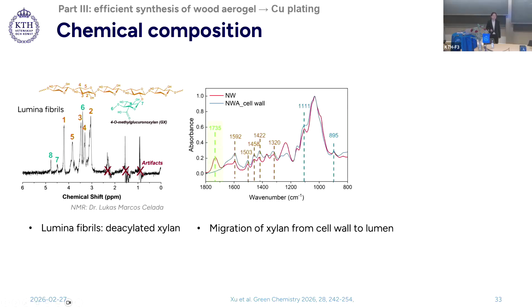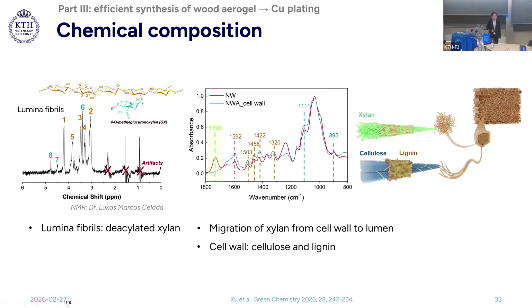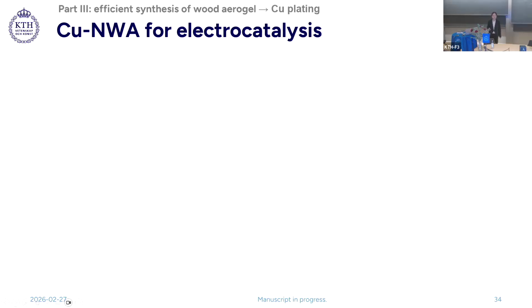Meanwhile, characteristic bands of lignin and cellulose remain. In a word, the lumina fibrils of native wood aerogel primarily consist of deacetylated xylan, while the cell wall of wood aerogel is mainly composed of cellulose and lignin. The highly mesoporous structure of wood aerogel provides a great platform for subsequent functionalization. Here, electroless copper plating was applied again on the wood aerogel due to the great properties of copper.